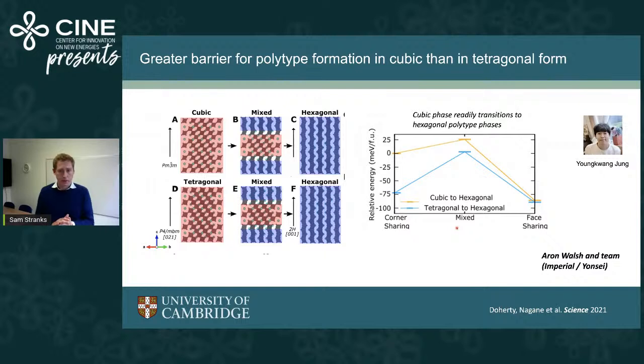And why this is important is because, so this is some work done by Aron Walsh and his team, where we're looking at the phase transition from a cubic phase to hexagonal phases, these polytypes, comparing that to the tetragonal and how that converts to hexagonal polytypes. And what we see is that the activation barrier for that conversion to these unwanted phases is much higher for the tetragonal phase. So if it starts in this slightly tilted phase, it's less likely to convert to these unwanted hexagonal phases compared to the cubic phase. So if it's in the cubic phase, it will quite readily transition to these hexagonal phases.